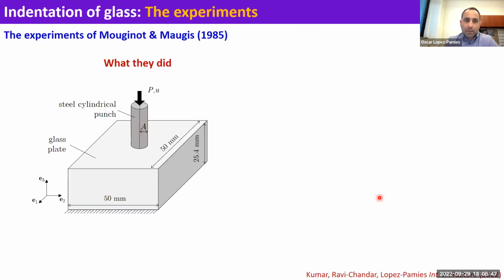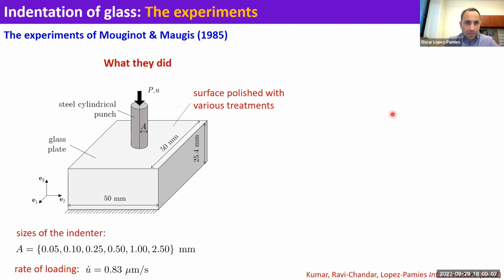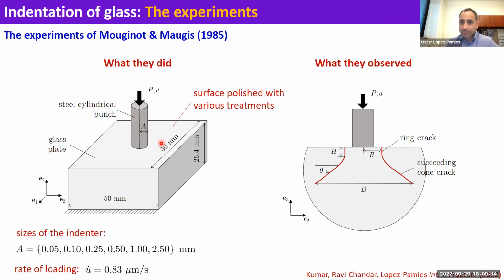All right, so back in the 80s, Mouginot and Maugis made some careful experiments where they were controlling what type of glass they were indenting. And these are the details of the geometry and the indenter. They take a metallic indenter and they apply a force. And what happens is this. At some point, if the force is sufficiently large, cracks nucleate as ring cracks. And if you continue to apply load, these ring cracks then turn and they become cone cracks. And this is how fracture nucleates and propagates in glass due to indentation.